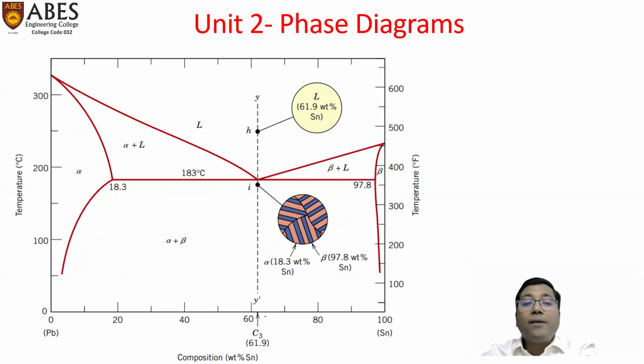Similarly, when you consider the C3 point, what is C3? It is the eutectic point. So if we go down from this H point, we consider the 61.9 weight percent tin combination at 250 or 255 degrees Celsius, this is completely liquid. And when we reach the eutectic point and just below it, we have just two types of solid, alpha plus beta. The weight percent of alpha would be 18.3% and beta would be 97.8%. And this is in the form of alternate lamellae, alternate layers of alpha and beta. This is the typical alpha plus beta combination, and till room temperature it would be like this.